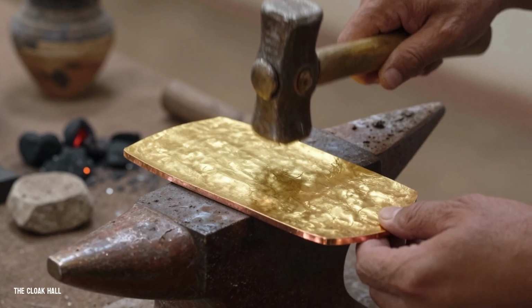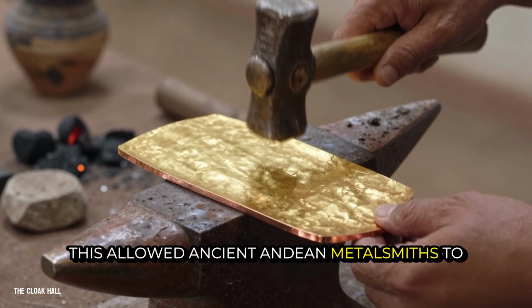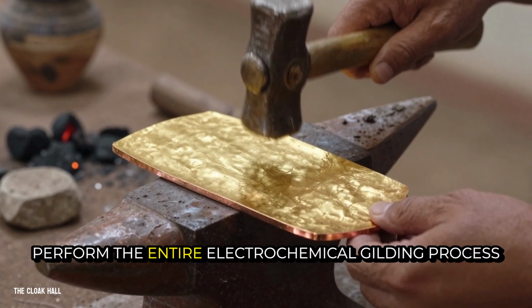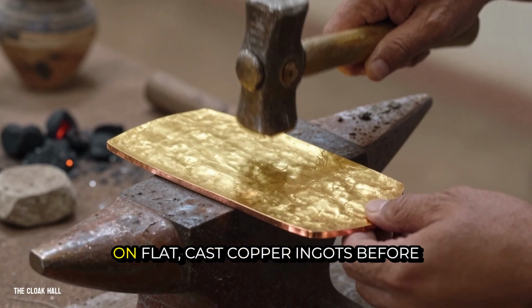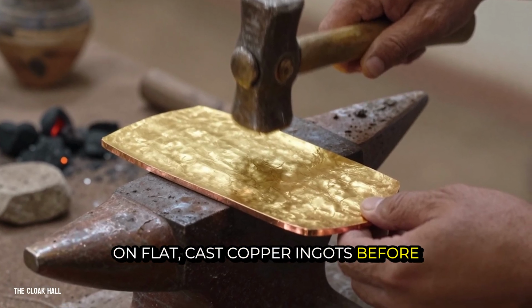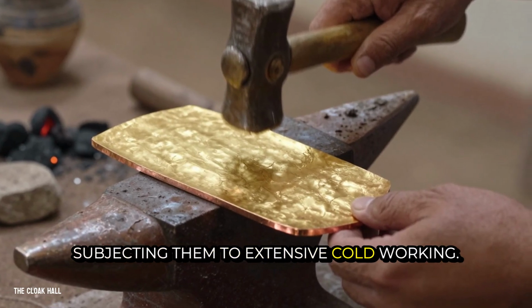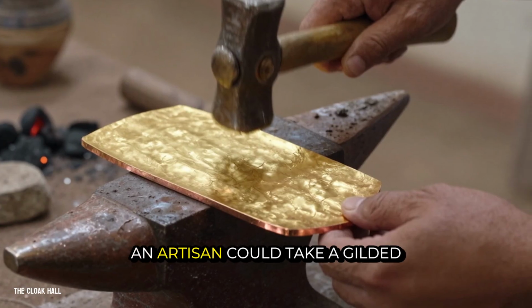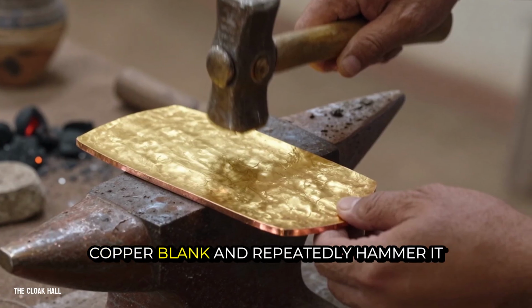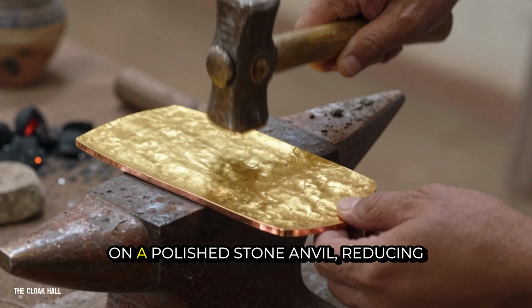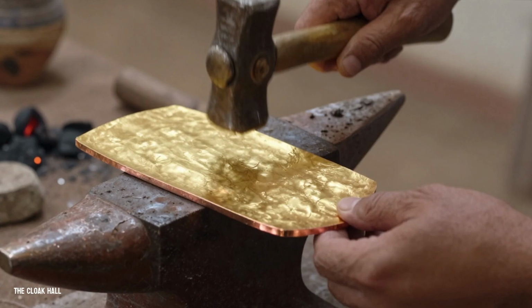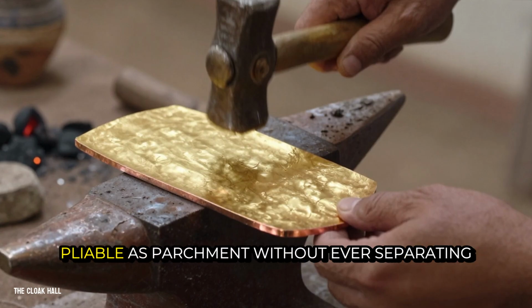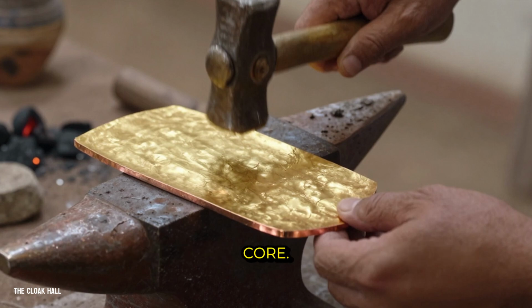metallic sheet. This allowed ancient Andean metalsmiths to perform the entire electrochemical gilding process on flat, cast copper ingots before subjecting them to extensive cold working. An artisan could take a gilded copper blank and repeatedly hammer it on a polished stone anvil, reducing its thickness until it became as pliable as parchment without ever separating the gold skin from its copper core.